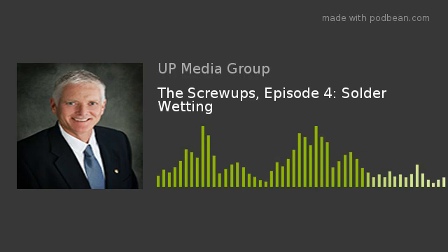So we have to make sure that the product is stable yet active enough to meet, I would say, 80% of the market requirements. So that's how we have to balance things and how we can address a non-wet. And then a dewetting condition is typically related to process, typically profile related, typically time at temperature related, be it surface mount, be it wave, be it hand soldering. There are a lot of other variables to consider in that calculation as well.